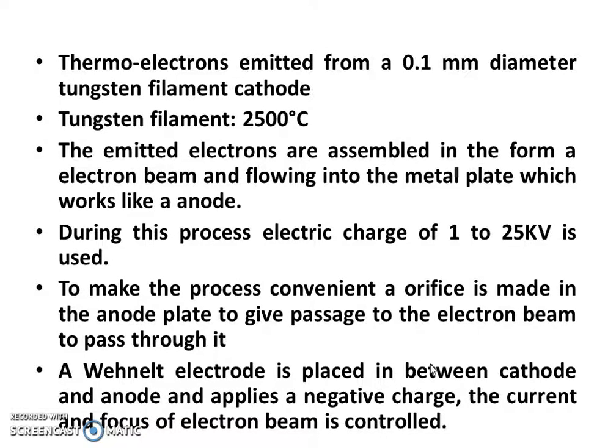Thermoelectrons are emitted from a 0.1 mm diameter tungsten filament based cathode, in the case of tungsten based electron guns, and the temperature goes up to 2500 degrees centigrade. The emitted electrons are assembled in the form of an electron beam and flow to the metal plate, which works like an anode. During this process, an electric charge of 1 to 25 kilovolt is used, and the amount of this charge depends on the quality of the image and the type of system which is going to be scanned. To make the process convenient, an orifice is made in the anode plate to give passage to the electron beam. The Wehnelt electrode is placed in between the cathode and anode and applies a negative charge. The current and focus of the electron beam are controlled.